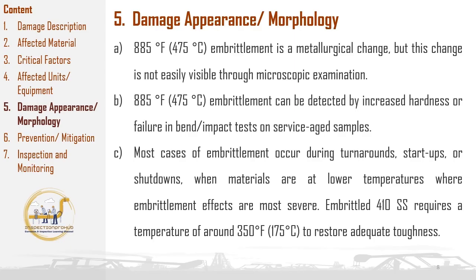Instead, the damage is primarily identified by a loss in mechanical properties, particularly a reduction in impact resistance, which can increase the risk of brittle fracture under stress. Specialized testing methods that measure changes in mechanical behavior, such as impact testing, are therefore required to detect this type of embrittlement. Embrittlement at 885 degrees Fahrenheit occurs when materials are subjected to prolonged high-temperature exposure, causing microstructural changes that degrade their ductility and toughness. This process can be detected by an increase in hardness, indicating a loss of toughness and heightened brittleness.